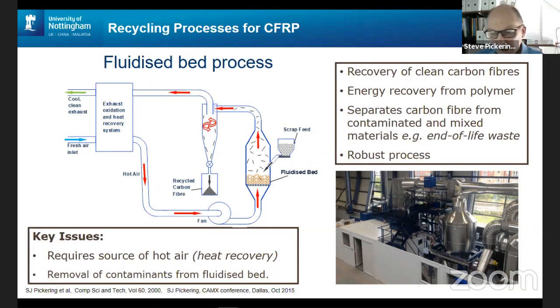and in that process, working at typically temperatures about 550 degrees C, the polymer would be effectively broken down and oxidized, leaving behind the individual carbon fibers, which would then be carried out in the airstream from the bed, and can be separated out to give clean fiber waste here, and the gas stream can then go on for further oxidation and heat recovery, and you use the recovered heat to recirculate round again, with the air going through the fluidized bed. So you can recover very clean carbon fibers.